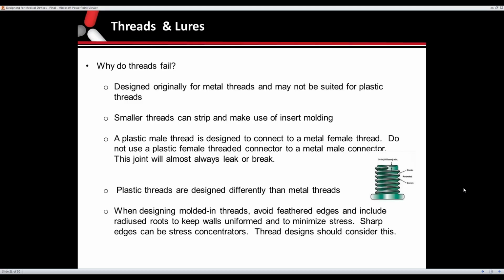Threads and luers. Typically we see a lot of luers on medical parts that we do here. When dealing with threads, we get a lot of customers switching from metals to plastics, and the way you design metal threads is completely different than designing for plastic. So there are some rules that you have to follow. Using smaller threads can strip from the mold. If you're designing a male thread on your plastic part, that works well. With a metal female thread, you really don't want to go the other direction on that, as far as having that mating surface and as far as leakage and things like that.